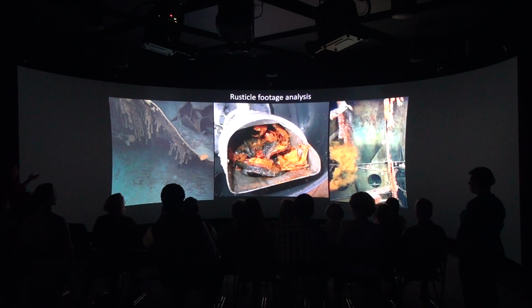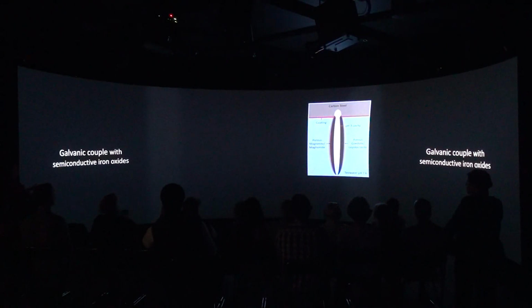But this image was really, really informative, because you can see there's a black inner portion of the rusticles that you don't see in these other images. So that was really informative, especially this difference between black and orange iron oxides, because these black iron oxides may be semiconductive. For example, this is what I envisioned, after doing all this analysis and looking at that picture, the rusticles are like inside. So this is just like a slice of the rusticles, and it has the inner cavity that, as I was telling you, is acidic inside.